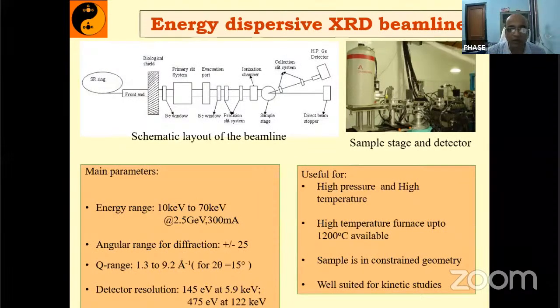Then, just like our angle dependent X-ray diffraction, there is energy dispersive X-ray diffraction. Because in our synchrotron a continuous energy source is there, one can have a one shot X-ray diffraction system. Because of the one shot, any kind of dynamic experiment can be done using X-ray diffraction. In angle diffraction, you have to scan, and scanning requires a minimum time. But here one shot experiment is there, so you get the X-ray diffraction in one shot. So one can do a dynamic experiment. You can increase the pressure, increase the temperature, or do any kind of chemical reaction inside the material, and you will get the immediate X-ray diffraction result of that material. So energy dispersive X-ray diffraction is also available.